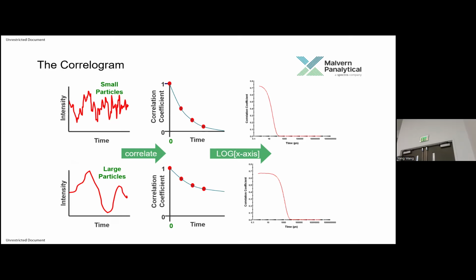When you say that the baseline tells you the quality, is that you don't want any peaks on the baseline? Yeah, so sometimes what happens is that if you've got dust or contaminants in the presence of your main population, it might present a noisy baseline or a raised baseline.